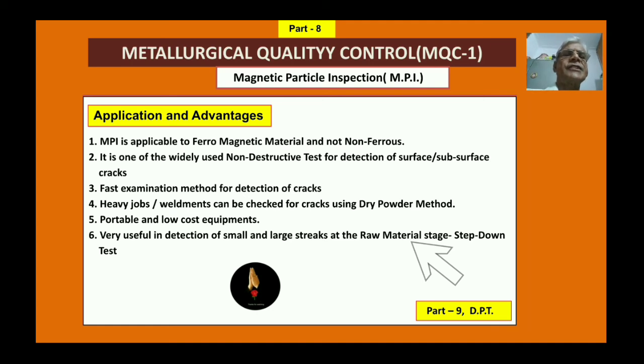The third point is fast examination method, because if you check the cracks by any other method, sometimes people do acid etching, pickling or something, but it takes very long time. But when you do this magnetic particle inspection, it takes very less time, and the accuracy is also quite good in case of subsurface or surface cracks. So that accuracy as well as quickness is there. Wherever the production requirement is very high, then you have to use only MPI, no other technique.